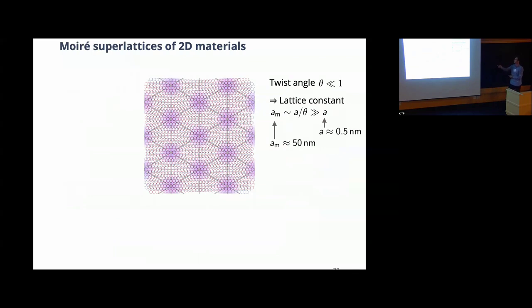For example, if you have a honeycomb lattice with a lattice spacing of roughly half a nanometer, and you pick a twist angle of roughly 1 degree, so this is much smaller than a twist angle of 1, you get an emergent lattice constant which is now 50 nanometers. That's basically two orders of magnitude larger, which is really unheard of. Typically, in condensed matter physics, if we grow different crystals, we realize different lattice constants, but they all stay in the same order of magnitude of a few nanometers.